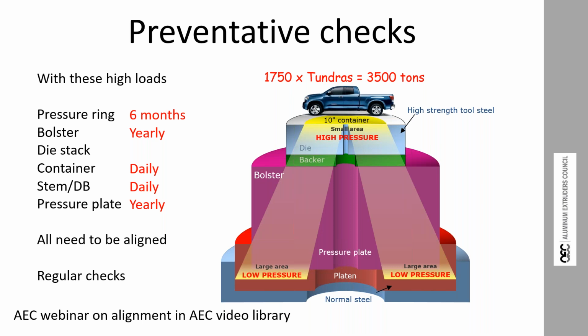The clean out block, well, you should always run that with alloy changes, so you don't contaminate alloys with the previous alloy that was in there, and you get a free check between the stem and the container. And I'll say a little bit more about that in a second. But don't forget the pressure plate that sits behind the stem. That's the bit people forget to check. That needs to be checked as well yearly. And all these things need to be aligned, clean and parallel.